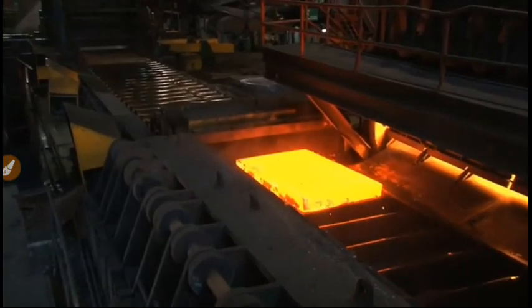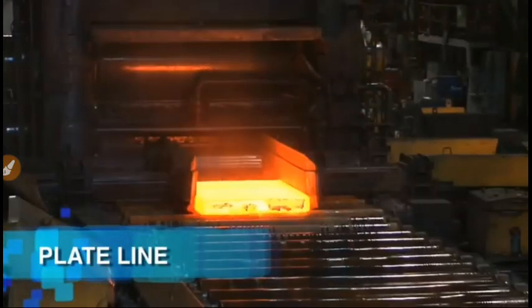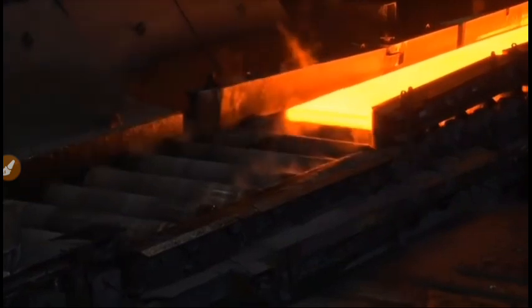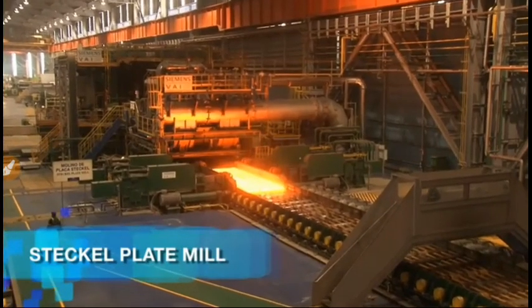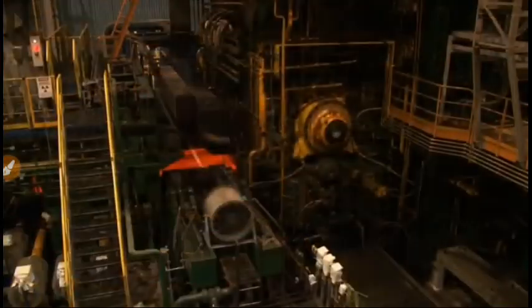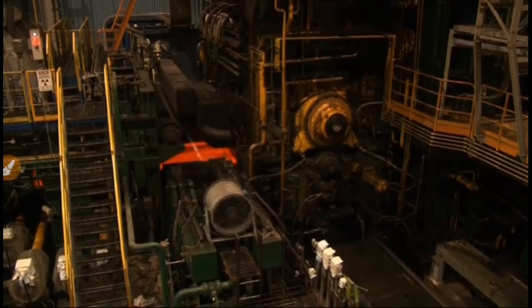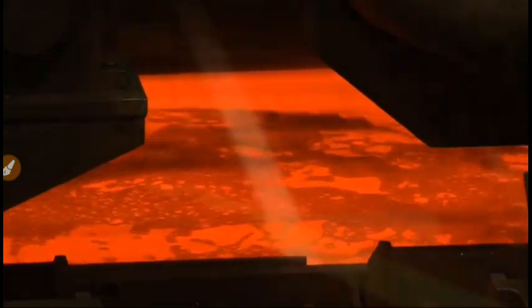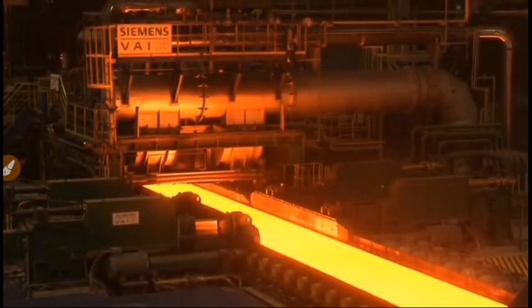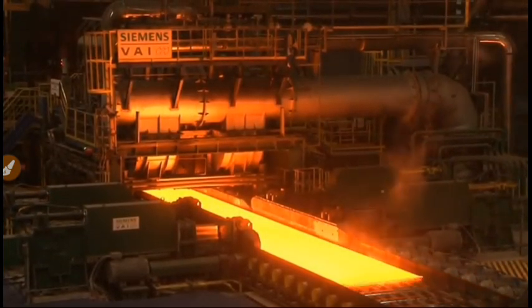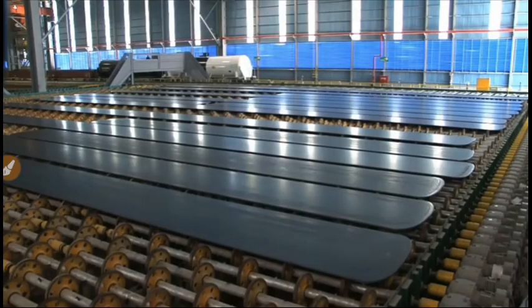Plate line 1 has two reversing mills that in a series of passes generate wide plate in the required thickness and width. On plate line 2, the 8-inch slab is rolled in a reversible Steckel mill, and the steel strip is temporarily stored in closed box furnaces to maintain temperatures above 1,000 degrees Celsius. Subsequently, an edger mill reduces the width of the strip to produce plate in sheet or coil.